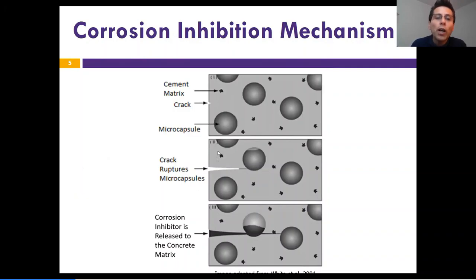When you have a crack in the concrete, you see the crack on the top, and then the crack starts to propagate. With the crack, you have a full exposure of the environment to the microcapsules, and the microcapsules can release these chemicals, which either precipitate or act chemically on these corrosion precursors, again to extend stage one and make it last longer.